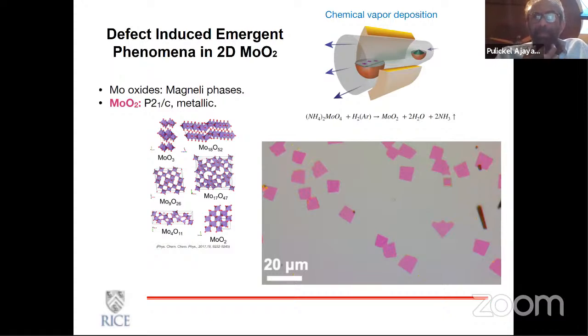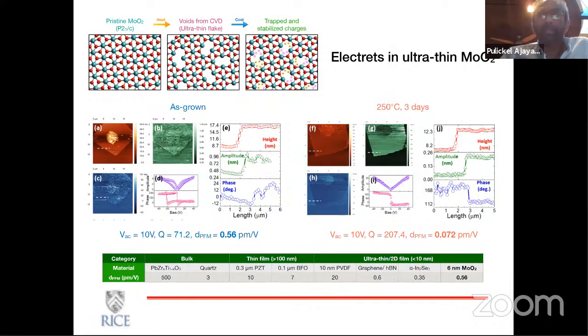We mostly talk about sulfides and selenides, but there are also oxides which are interesting. Molybdenum dioxide, which is not really the most thermodynamically stable oxide, has some very interesting properties. And particularly, we recently pursued the idea of electrets. And this happens because of the intrinsic stoichiometry defects. You can create polarized charges, and although molybdenum oxide is not really a piezoelectric material, because of these intrinsic defects that appear from non-stoichiometry, you can create piezoelectricity in these layers. This was recently published in ACS Nano. You could actually go and look at it.